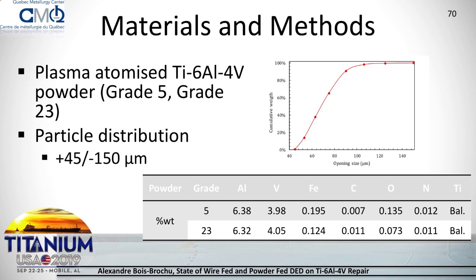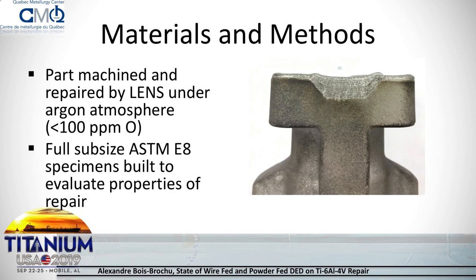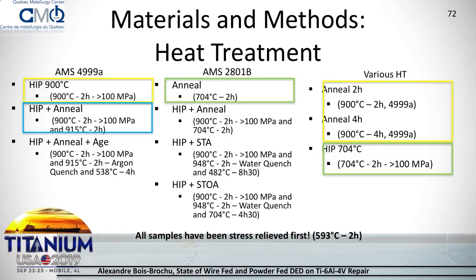So here we can see the part. It showed porosity on the top section. It was all machined and rebuilt using the LENS system, all under argon atmosphere. And following that, because it's a horizontal repair, we produced multiple samples to evaluate the properties of such a repair. For the heat treatment, the standard for repair with DED for titanium is the AMS 4999A. The original heat treatment that we used was based on DED, using the HIP plus an annealing, but the annealing is at a fairly high temperature at 915.